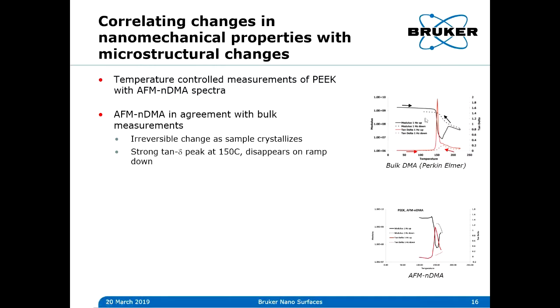So, and then when you change the temperature back down to lower values again, now this peak is significantly reduced. And in fact, it would completely disappear if there were no amorphous peak available any longer. So there's a little bit of amorphous material still left in the sample. The AFM nano-DMA measurements agree very well with the bulk measurement. We see the same drop in modulus and the same increase in modulus, and we see the sharp peak on the way up, and we do not see a sharp peak going down.